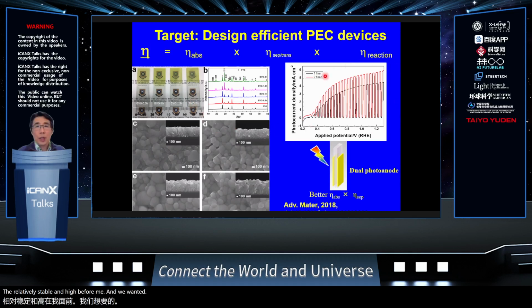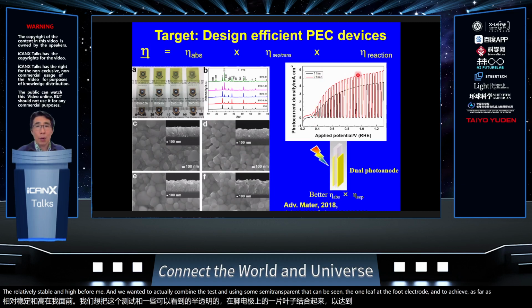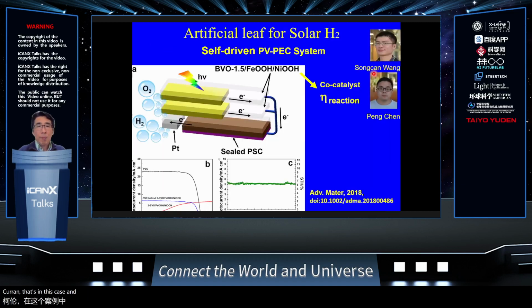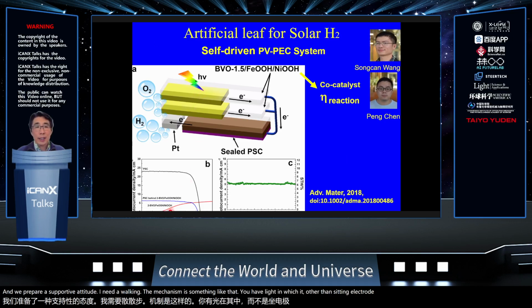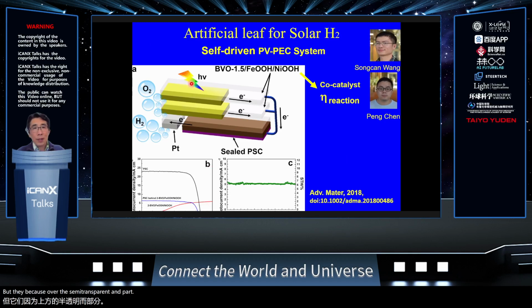We wanted to combine some semi-transparent material as the photoelectrode to achieve as high a photocurrent as possible. In this case, by combining this photoelectrode with a solar cell, we prepare a so-called artificial leaf. The working mechanism is that light irradiates the photoelectrode and generates photocurrent, this red curve. Then, because of the semi-transparency, part of the light passes through and activates the back side perovskite solar cell, and in this case generates another photocurrent.